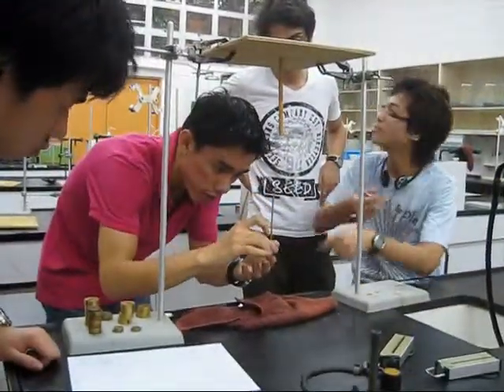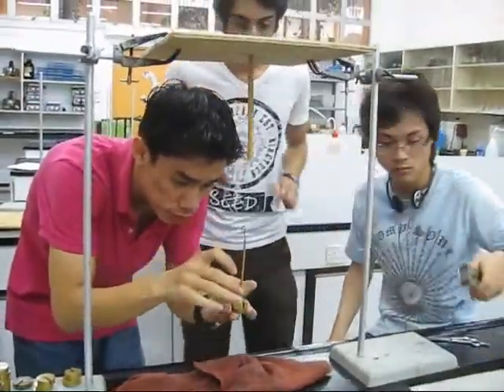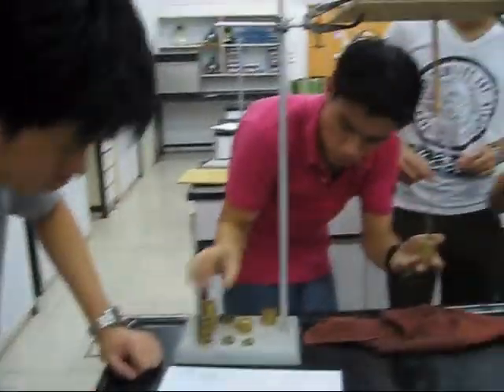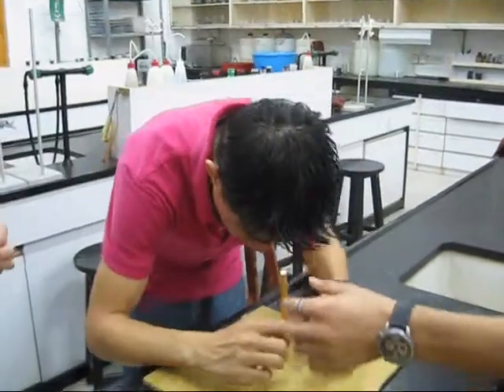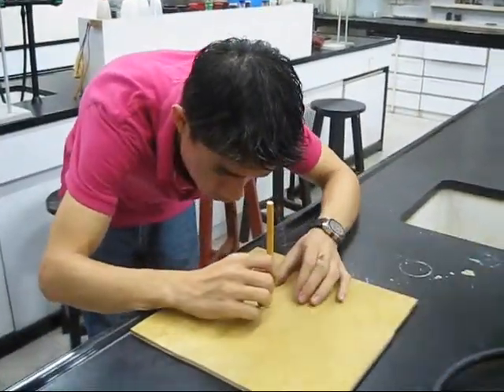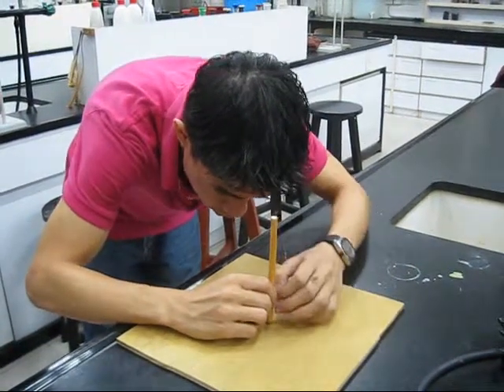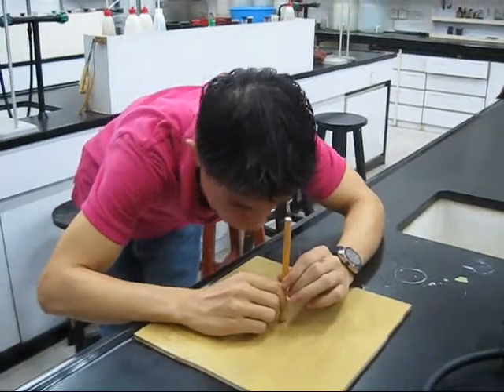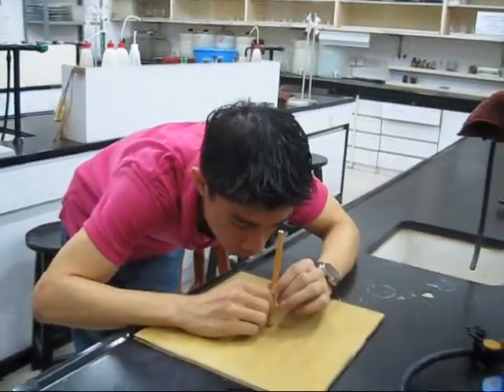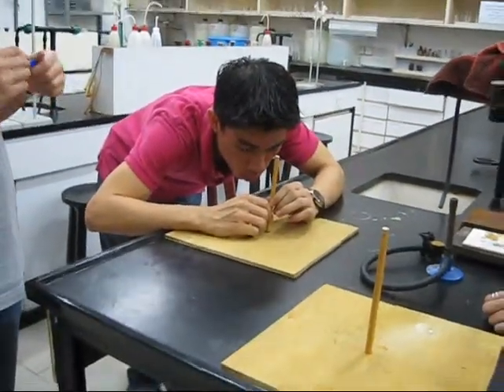When testing for tensile strength, the board and the retort stand were mounted so that the sticks would be perpendicular to the table. This would test the pull strength of the glues to keep the stick and the board surface in contact. Nylon string or fishing line was tied to the end of the stick not bonded to the board for tensile, and the end of the stick bonded to the board for shear. Prior grooves were made on the sticks so that the strings were more secure.